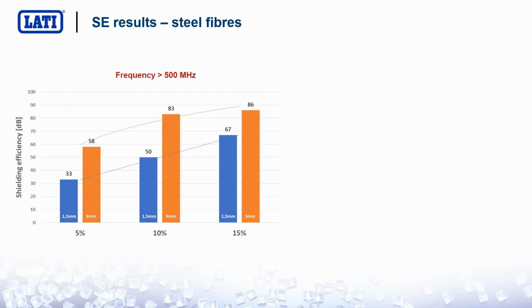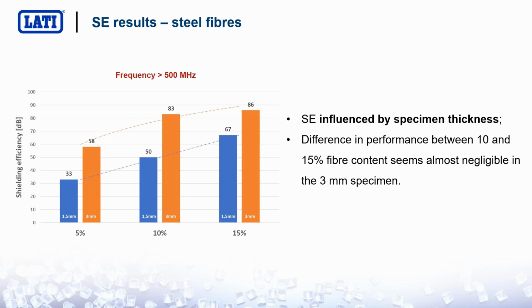We can also see the same results here in this other graph, where it is evident that for higher thicknesses, there is more or less no improvement by increasing the content of stainless steel, and noting that higher thicknesses are more efficient than lower thicknesses. This is something that we must keep in mind. If you want to use steel fibers as additive for electrically shielding compounds, you must always think of wall thickness as a critical factor for your device. So it's not only how much fiber you put inside, but also how thick your walls will be.